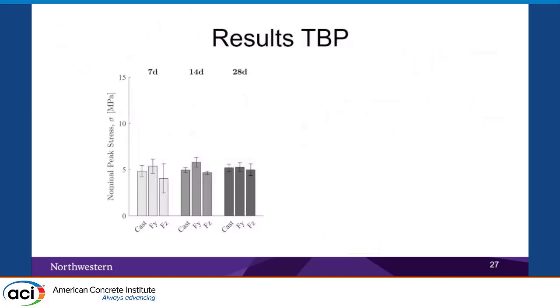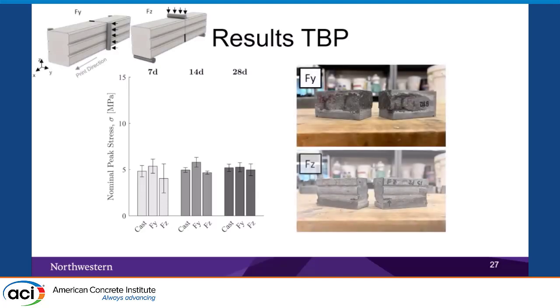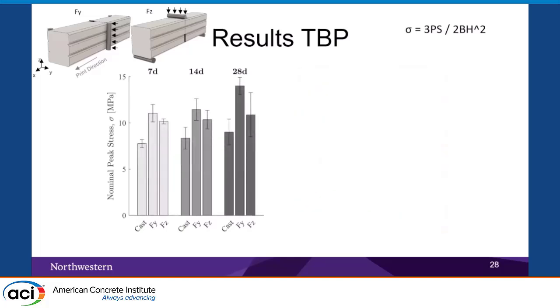When we look at the 3-point bending results, the capacity of the printed samples compared to the cast samples is almost equal, and you can see the failure mode is exactly at the notch. Then when we added fiber, the printed sample has higher strength compared to the cast samples, and this is because of the fiber alignment in the Y direction and in the Z direction.